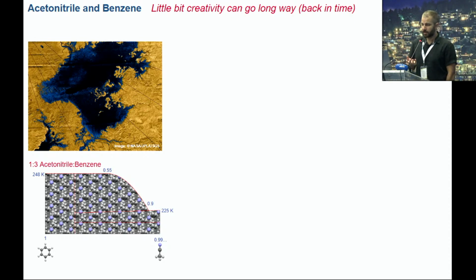We can use them for looking back in the past. Now, the lakes of Titan evaporate and then precipitate again. So that's a very dynamic environment. We do know that there are regions on Titan that used to have lakes, so they're lake beds. The lakes are made of ethane. Ethane and acetonitrile are quite similar in shape and size. So our hypothesis was that if acetonitrile forms a co-crystal with benzene, it can interact with ethane, and we can have a ternary co-crystal, or some sort of reaction between those two molecules.